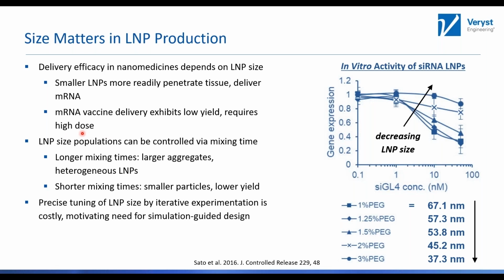Now, LNP size can be controlled via mixing time. In general, longer mixing times give lipids more time to aggregate and hence lead to larger aggregates and more heterogeneous size distributions, while shorter mixing times lead to smaller nanoparticles, but at the same time, lower yield. And we'll talk more about mixing later in the talk.